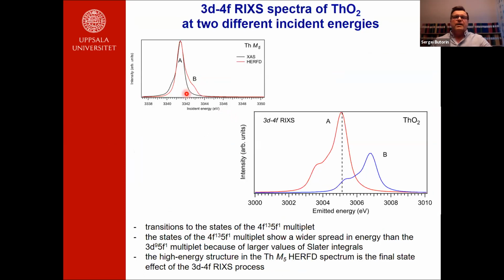The differences on the high energy side of the HERFD spectra are easy to understand by looking at the example of thorium dioxide. For thorium dioxide, the 3d9 5f1 multiplet has its highest state at the energy of this strong peak. So there are no other states of this multiplet, while we still see some structure in the HERFD spectrum of thorium dioxide here. To understand why it appears, you should look at the RIXS spectra actually taken at these incident energies A and B.